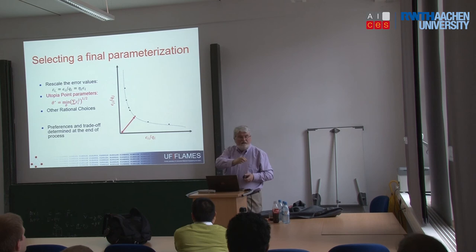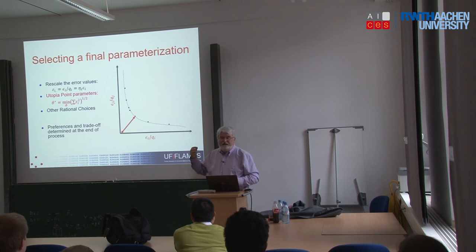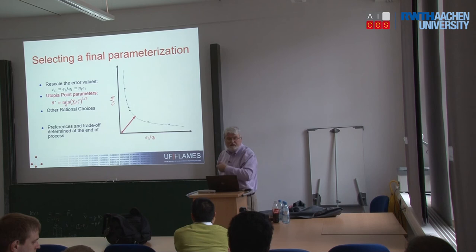And we can say, okay, I've changed my mind. I've changed my mind for this problem. It's really important I get the defect energies right. I can go back and look at the same data set, essentially, and pick out a new potential. So this is a completely algorithmic process to the point where we make the final parameterization selection. It's completely automated. We have Python scripts calling LAMMPS calls, doing all that stuff automatically.